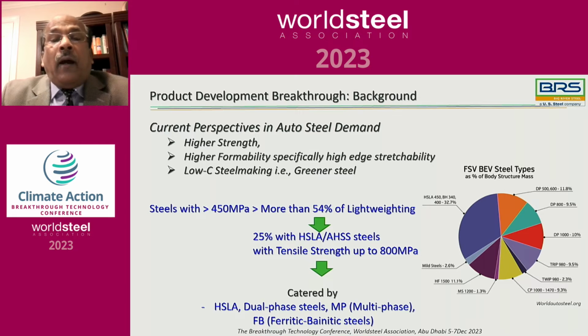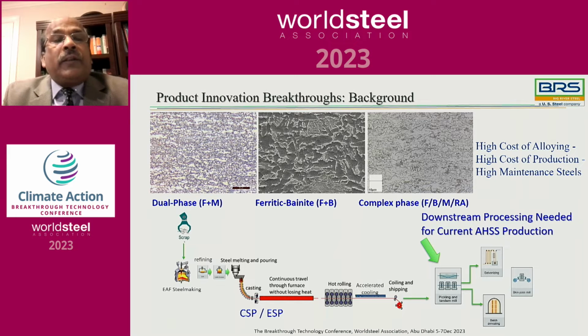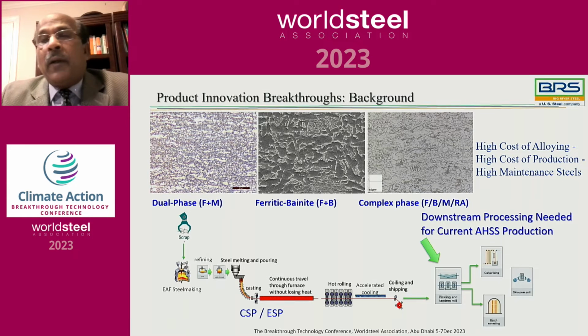And next, if we look at these dual phase, ferritic bainitic, or complex phase steels, in order to guarantee these microstructures, these steels are highly alloyed, and the cost of production is very high. To generate this second phase microstructure, to get strength and formability, downstream processing is needed, like very complicated finishing lines. So the thought process was: how about taking out the second phase particles, making a single phase ferritic microstructure, and getting rid of the whole secondary processing lineup? So that's what we are talking about here. Next, please.